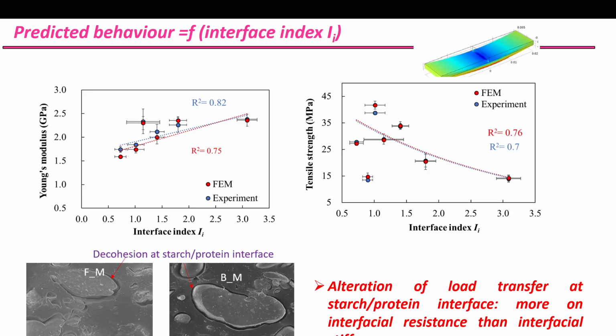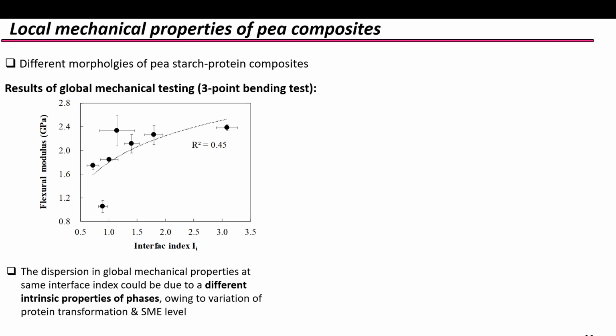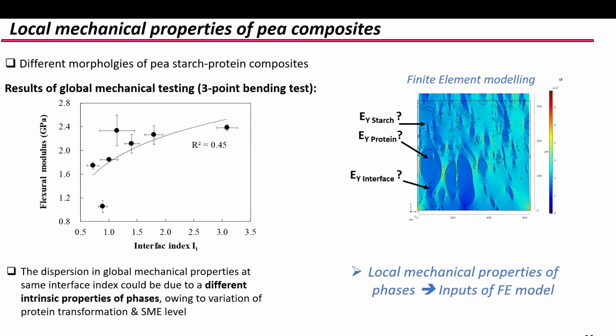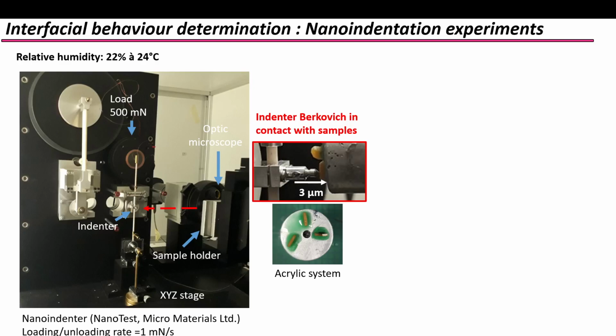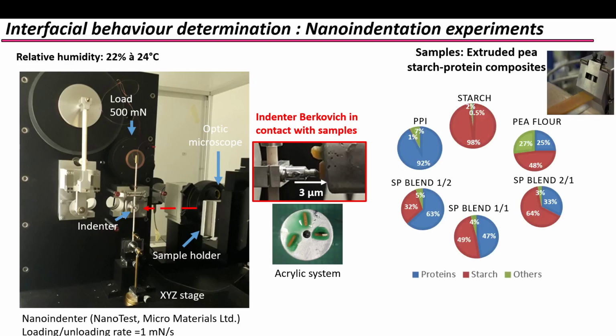So this is the main hypothesis that we used, and we wanted to verify this from the nano indentation results. For that, we needed more information to be able to do the micro-mechanical models that Imens tried during his thesis. So the basic idea is how to determine both the phase properties, but also the interface properties as well. For that, we used nano indentation experiments at Imperial College, on all the samples that have been studied previously at the microscopic scale.